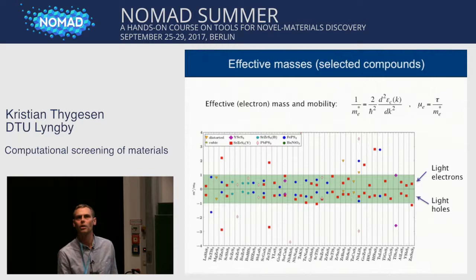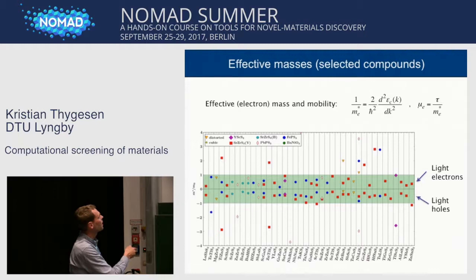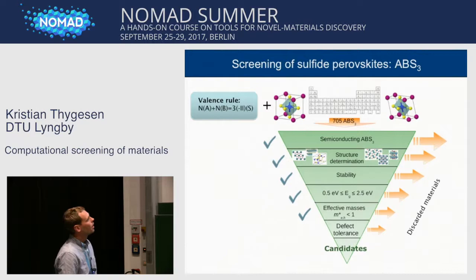And what we choose in the screening is to take only the materials that have effective masses for both electrons and holes that are lower than one. Okay? So that's a criterion we set. So all these materials in here represent hopefully high mobility semiconductors. Okay, the final thing we have here in the screening funnel is what I call defect tolerance.